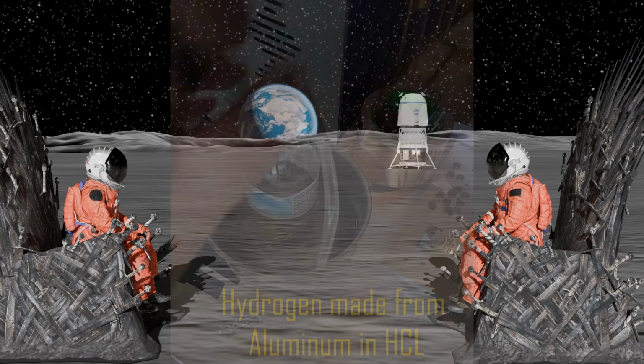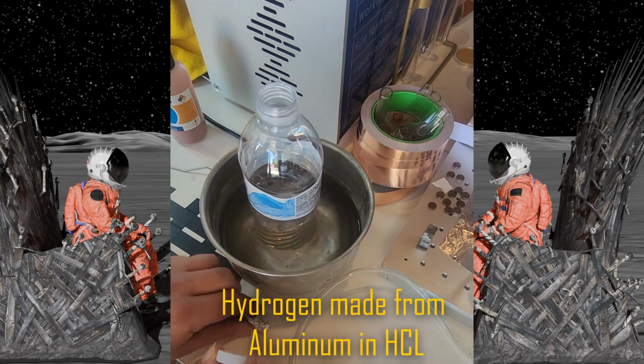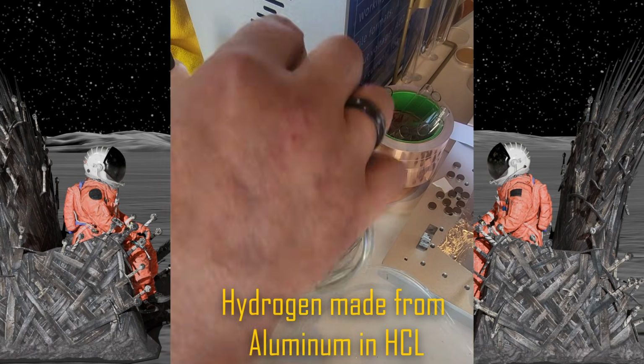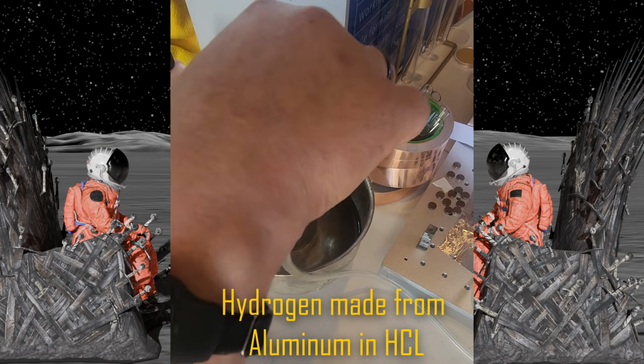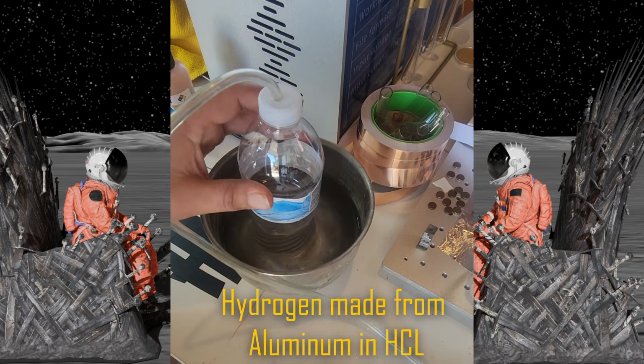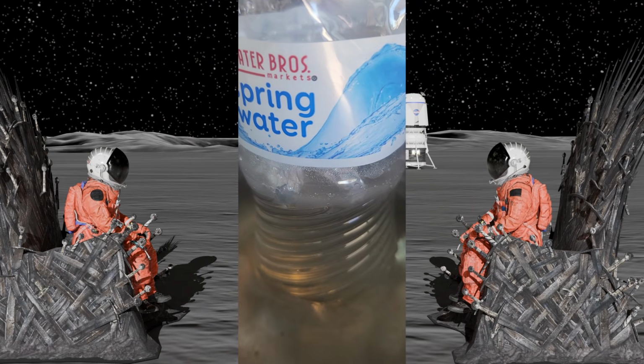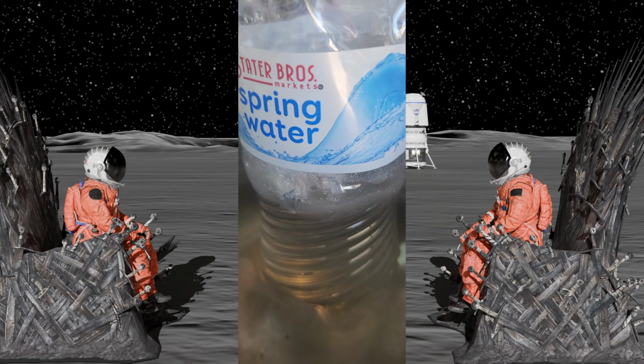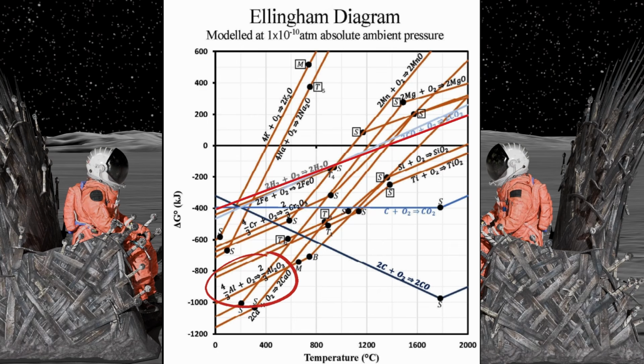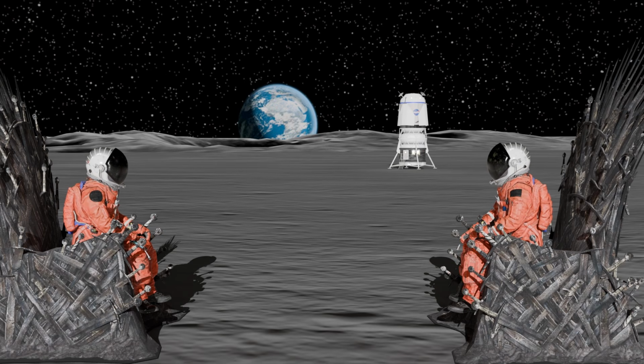So then a more friendly ISRU approach we did was to use hydrogen, which is a very effective reducing agent, and we should have it on the moon. And it's fully recoverable, meaning fully recyclable. However, it's somewhat limited in what it can reduce. For instance, it can't reduce alumina, silica, titanium oxide, calcium oxide, everything below it on the Ellingham diagram. But importantly, it can reduce iron, and quite effectively, correct?